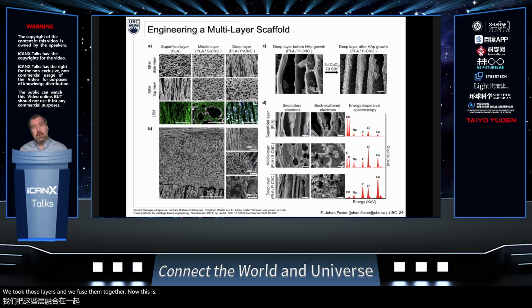Now this was non-trivial because cartilage for these implants is approximately 1 centimeter thick. So you need to get 3 different layers within that 1 centimeter of foam. We used solvent welding to get these to stick together, and then we pre-grew hydroxyapatite onto these.